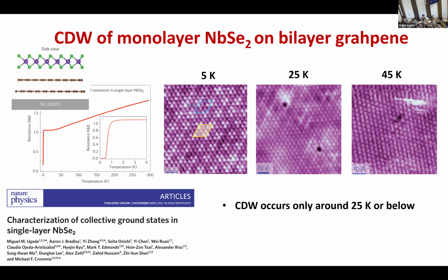Again, about the mismatch. I mean, how do the graphene and the niobium diselenide match? And maybe that's a very good point. So for this particular case, people argue that graphene is pretty flat, so you don't need to have a lattice match. It's like van der Waals bonding between them, which doesn't depend on the matching.